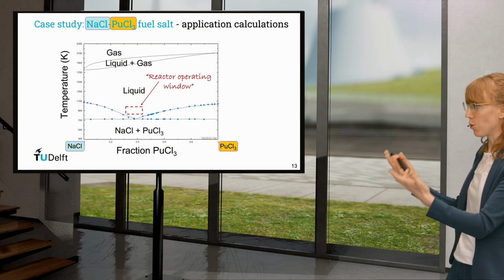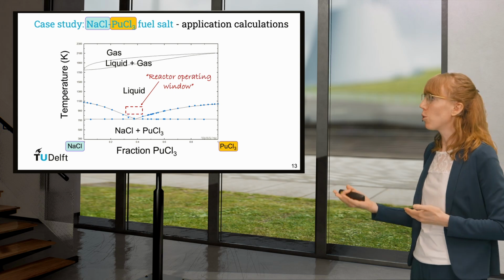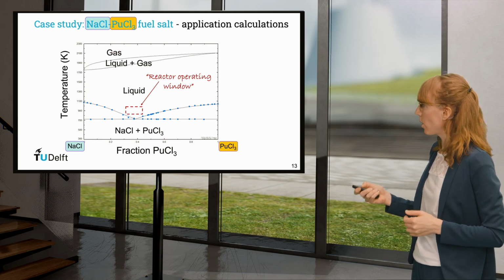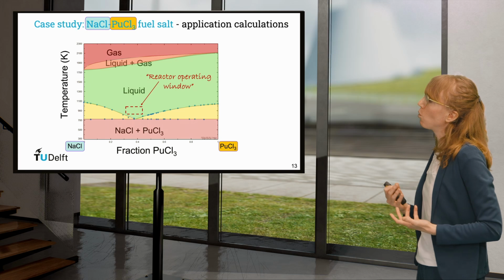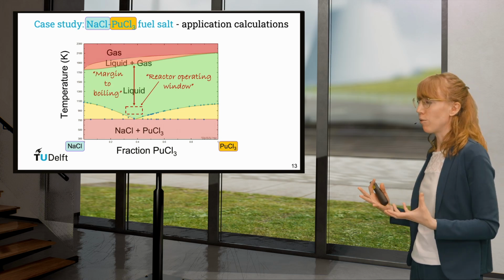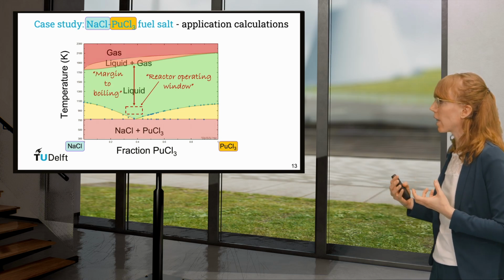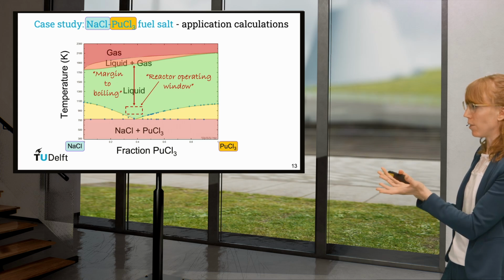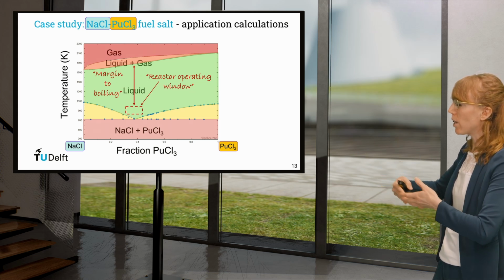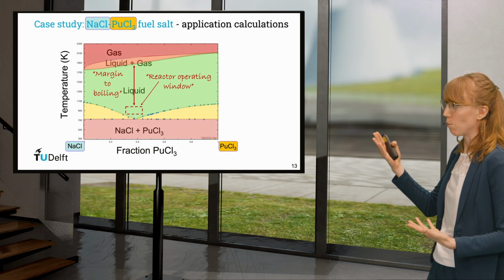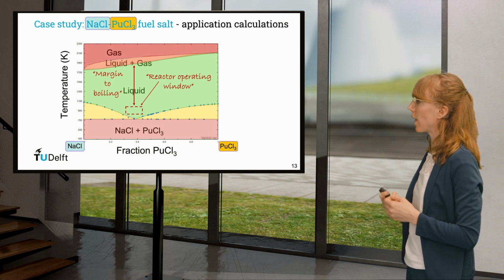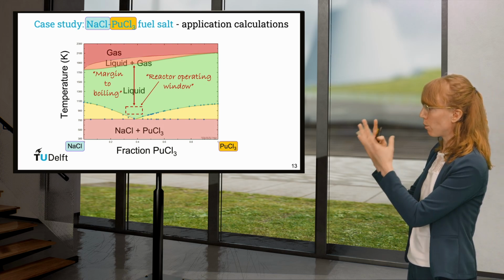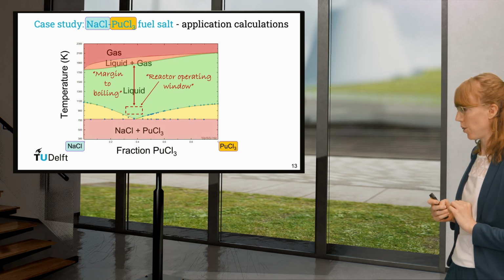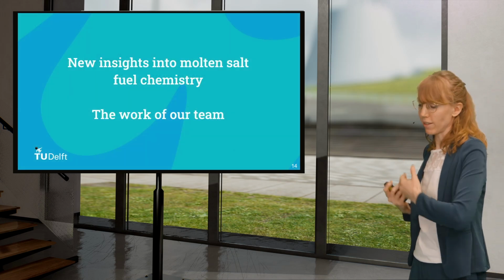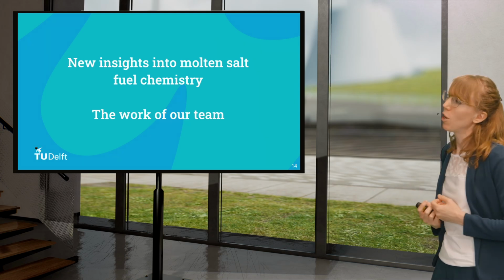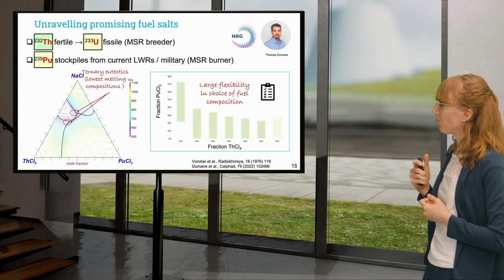We build models using the experimental data. We also include the gas in that model, and we know with the model when the gas is stable. So we get information on the margin to boiling. And you can see that if we operate in this window, we have a very large margin to boiling, to the temperature at which gas starts to form. So we can operate the reactor safely in that region. With that introduction, let's dive into molten salt chemistry done in Delft.